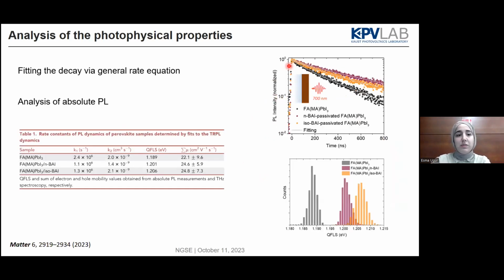When we fit the time-resolved PL decays, we're using the general rate equation that you can see. K1 corresponds to the Shockley-Read-Hall rate constant, and this is the radiative rate constant. Using the absolute PL, we can get the quasi-Fermi level splitting. As expected, since we are passivating the surface, the potential voltage output is also increasing. So it seems N-butylammonium or isobutylammonium, it doesn't matter, they work quite similarly and give quite nice results.